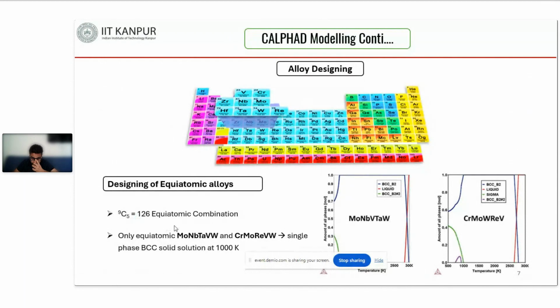From these 126 equiatomic combinations, we tested them for phase stability. We predicted their phase stability through a MATLAB code compiled with Thermo-Calc, and we found that from the 126 equiatomic combinations we got only two best alloys: the molybdenum, niobium, vanadium, tantalum, and tungsten alloy, and the chromium, molybdenum, tungsten, rhenium, vanadium alloy. These two alloys have a large thermal stability of phase. This is a single phase BCC phase, and it is stable over quite a temperature range. You see from 700 Kelvin to almost its melting point, it is stable.